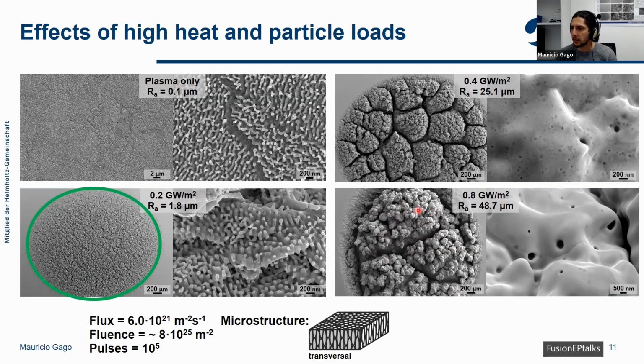I don't know if you can see it in the image, but there are small spheres or sphere-like formations on the surface. And this is clearly an indication that at some point some parts of the material were melted. And if we have melting on the surface, it means that the temperature reached the melting temperature of tungsten, which is around 3,400 degrees. And this is also not desirable because it will mean that the material can sputter more easily, or that the behavior of the material or its properties will degrade much faster.